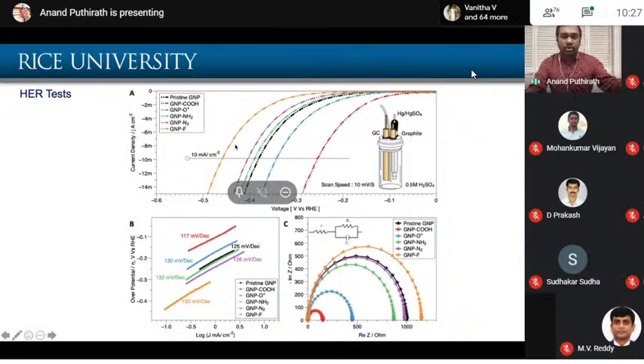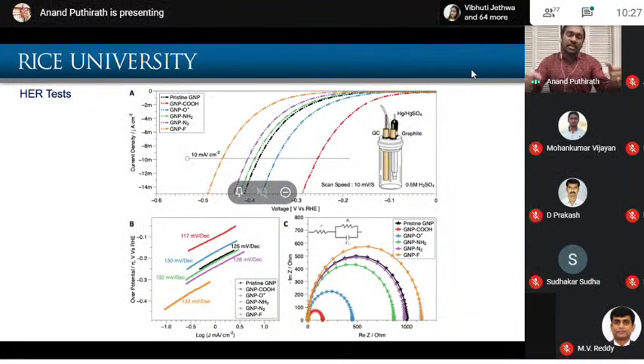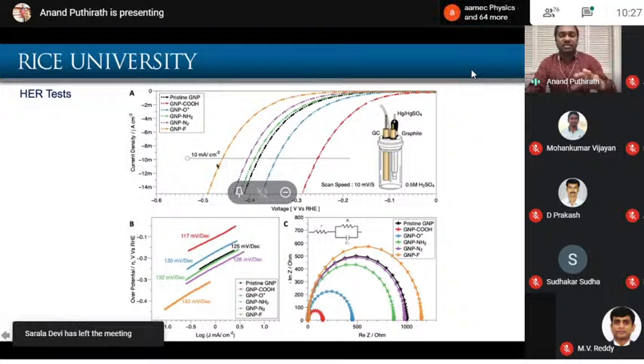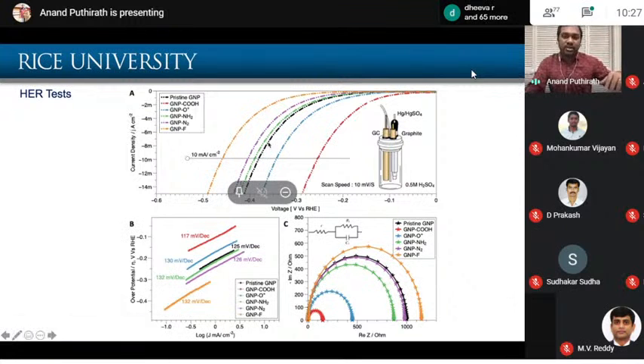That's the whole point of making catalytic material, so that you can reduce the net power or net energy needed to make hydrogen from water. So that's the whole point, right? And here, if you see, COOH functionalized graphene nanoplatelets is doing a better job, splitting water at lower voltage, and fluorine functionalized system is doing a bad job. It is decreasing the catalytic activity. This is our pristine sample, and it's going left and right depending on the functionalization.